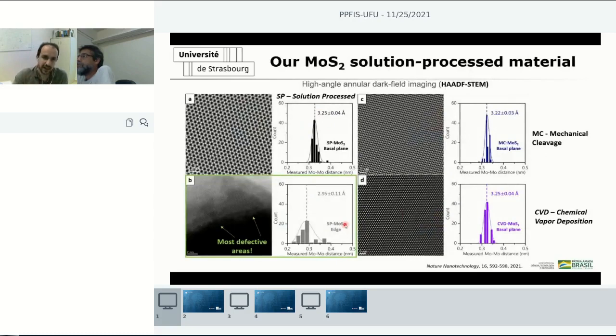Here is the high-angle annular dark field imaging of our films. So this in fact is our film. You can see here that it has defects over the flake edge. Here's the basal plane of one flake. If we measure the molybdenum distance for our material, we see that the variation is quite large.